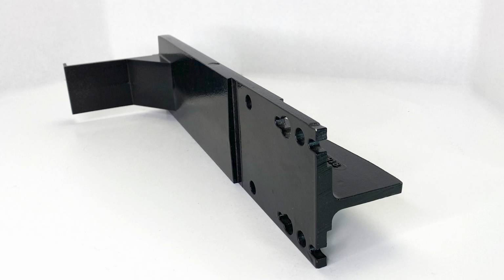Another thing to consider is if there are multiple different wall thicknesses in your design, think about how you would feed metal into those areas. If you have to flow through a really tight corner to fill the other side, you're going to start freezing off that other area. So if you're going to cast this, you have to design it so that it fills in properly. Castings have to have that transition between the thin and the thick. You can't do abrupt changes with your thin and thick walls.